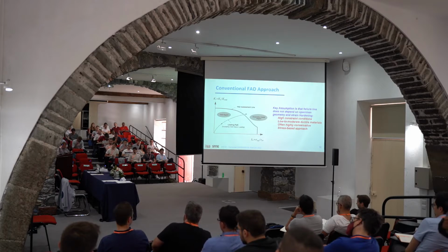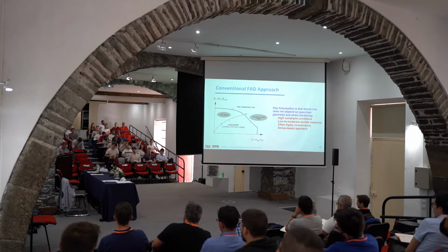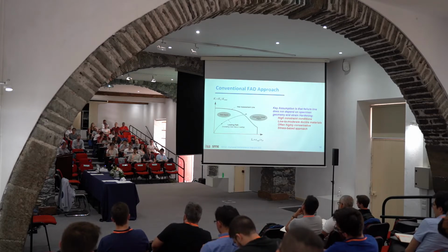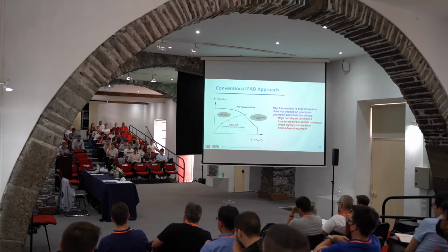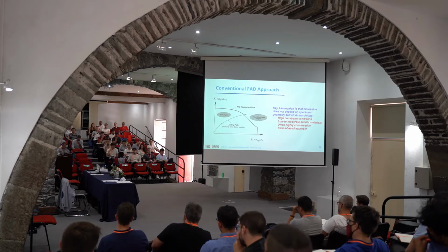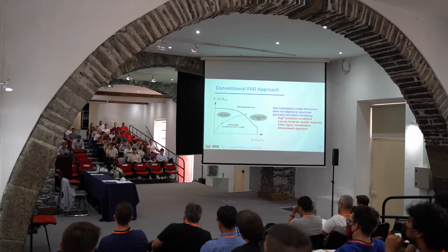When you have a crack, think of this. The crack, from the fracture mechanics side, is intensifying the stresses. That's why we call K the stress intensity factor, because it's intensifying the stresses. A sharp crack is actually a singularity. On the other hand, when you have a crack, you are also removing material of the pipe thickness. So the global stresses, actually the membrane stresses to be more precise, are increasing, because stress is force divided by area.